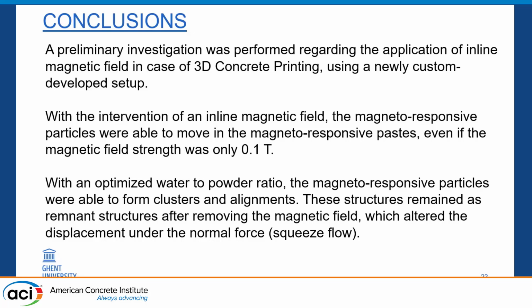So we had clear proof that clusters and alignment of particles was obtained, and important, due to the remnant magnetization, the structures at least partly remained after removing of these magnetic fields. And we saw the effect also under this squeeze flow test.